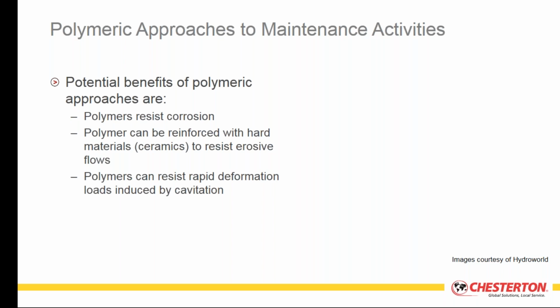So polymers are quite popular because they naturally resist corrosion, and there's a wide range of polymer-based systems. Probably the most common are the epoxy-based materials, which are co-reactive polymers based on a bisphenol A, bisphenol F resin chemistry. Normally, they're an amine-cured structure, so they are what we call chemically co-reactive coatings.